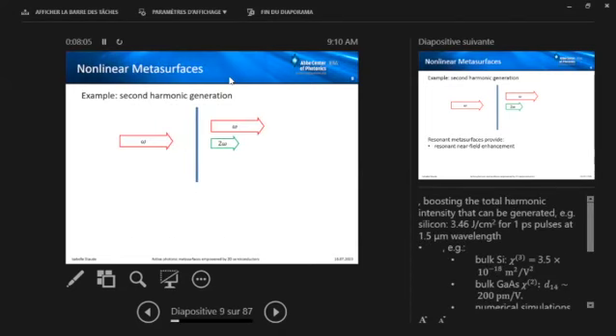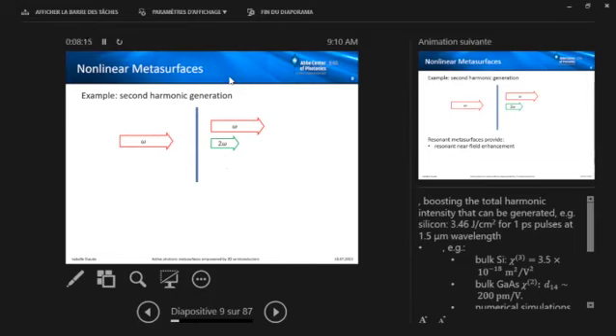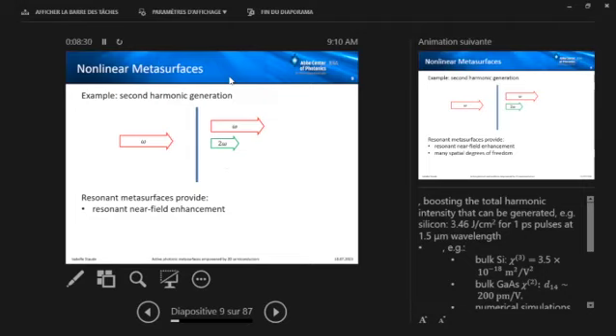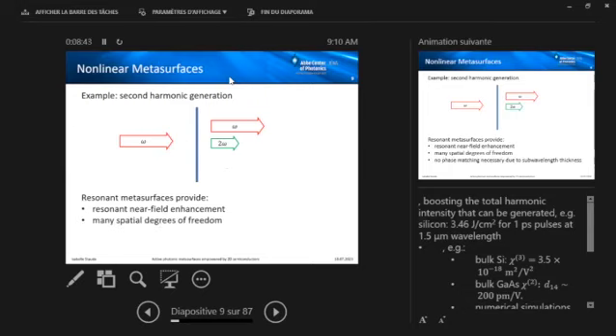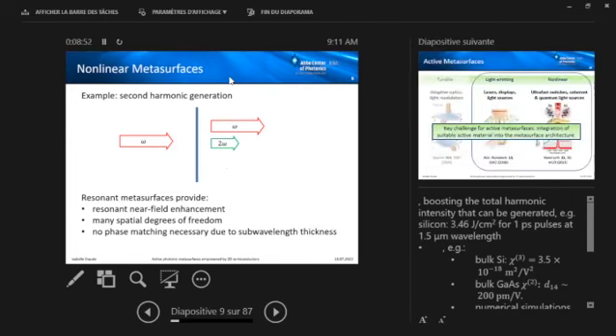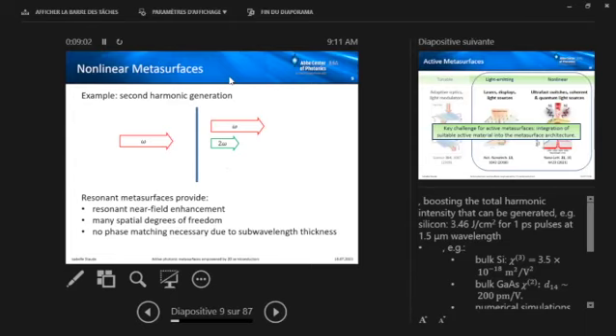What about nonlinear metasurfaces? So it's a huge field by itself. I concentrate here on the example of second harmonic generation. Again, I show you a little cartoon where here's the metasurface, and such a nonlinear metasurface, if we come in with a field at frequency omega, it can transform part of this into light at different frequencies. So for the example of second harmonic generation, light at two omega. And metasurfaces are very interesting in this respect because they provide this resonant near field enhancement, so that even from this nanoscale thickness sheet, we get substantial efficiency for this nonlinear conversion. Also, again, we have these many spatial degrees of freedom which can help us tailor the light at the generated frequencies. And maybe most importantly, because the metasurface is so thin, no phase matching is required.